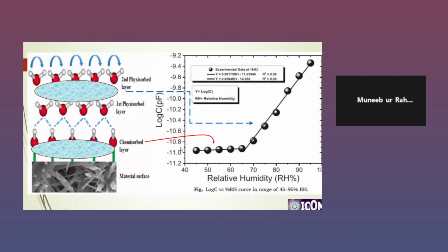We see that at lower relative humidity the capacitance increases very gradually, but above 60% we got another slope of the curve in which the capacitance increases abruptly. This is because of the first chemisorbed layer in the low humidity region when the surface was covered with water molecules. The next layers are deposited on this chemisorbed water layer in the physisorption, and in those physisorbed layers the H plus ion and OH ion migrate very quickly. That is why the capacitance of the device has increased abruptly.